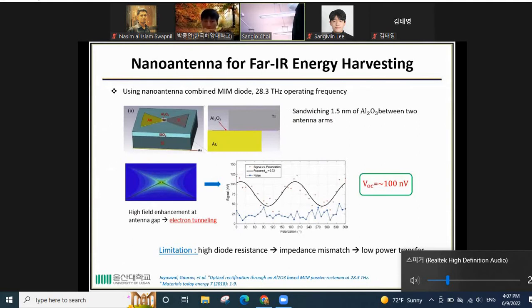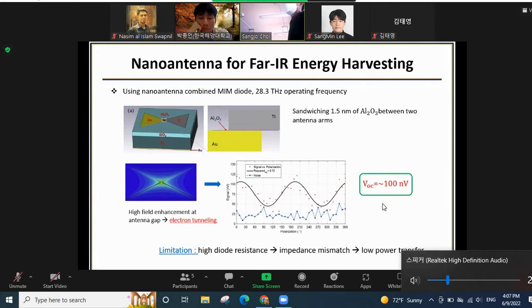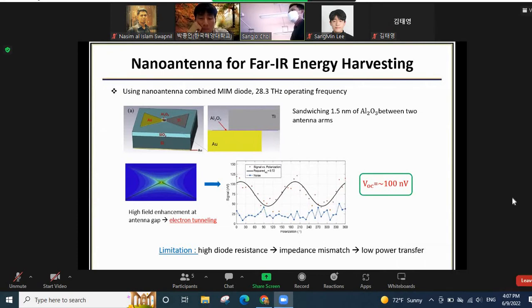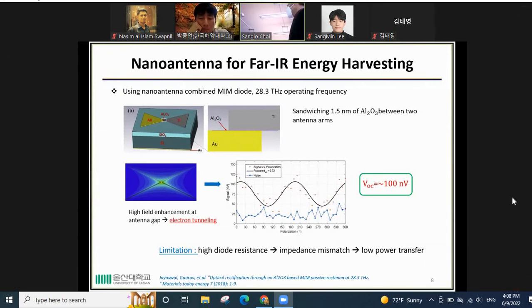Also, the nano antenna is used for far infrared energy harvesting. This is a nano antenna combined with an ultra thin layer, which is sandwiched between the two antenna arms. The electron tunneling happens because of the high field enhancement at the antenna gap, so this antenna shows a VOC response of around 100 nanovolts. However, this structure has some limitations like high resistance, causing an impedance mismatch between the antenna and diodes, so that this creates low power transfer.